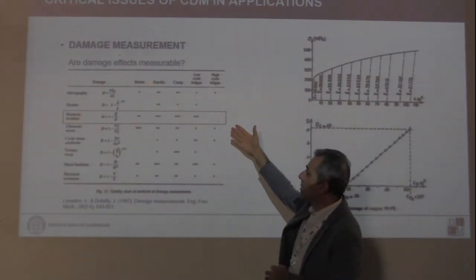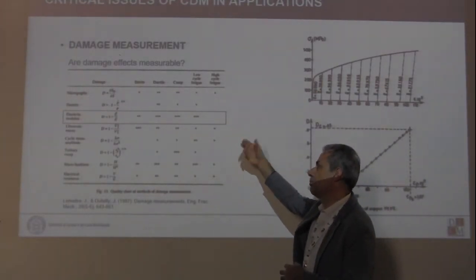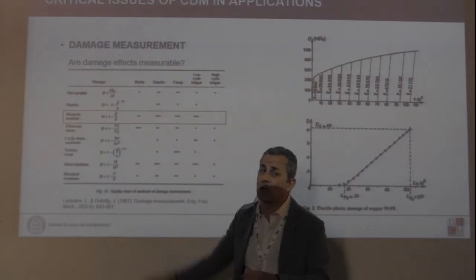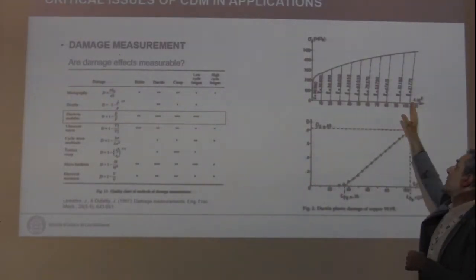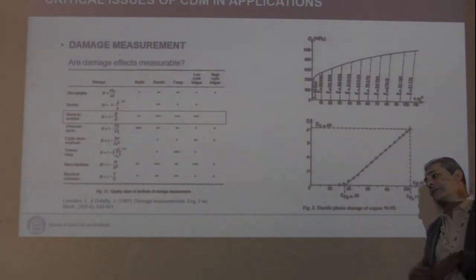The most commonly, the most accepted method is the stiffness loss. You perform traction, loading, unloading, and you should see variation of the elastic modulus, and this is a proof of damage ongoing. The problem is that, unfortunately, this approach is incorrect, and we demonstrate this.